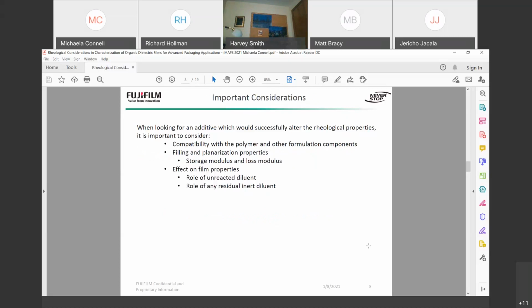So when we were looking for additives which would successfully alter the rheological properties, we also had to consider other important factors. One of those being the compatibility with our existing polymer and other formulation components. And another is, when we added these diluents, was it going to meet our filling and planarization needs? So in this case, we looked at storage modulus and loss modulus in order to determine if this would have effective rheological properties for filling and planarization.